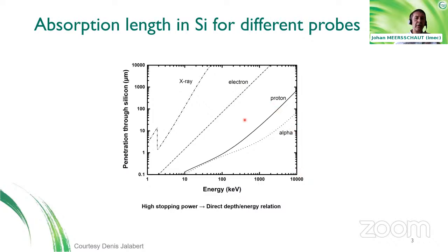The electrons, on the other hand, have a smaller penetration depth and therefore can have a better sensitivity to near surface phenomena. Then on the far left of this graph, you see that the hadrons, like protons, alpha particles, and so on, have a much smaller penetration through the material. This will have large consequences in their interaction with the material. The high stopping power of these particles, when they are energetically hit towards the sample, will make them, through their interaction, much more sensitive to near surface interactions.